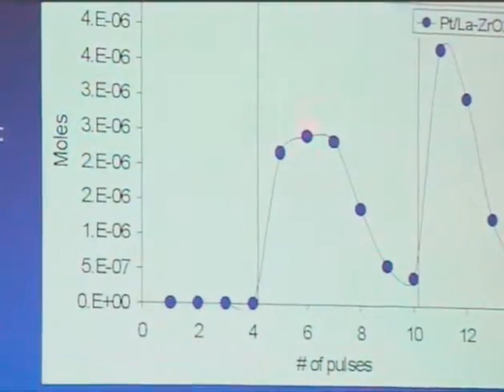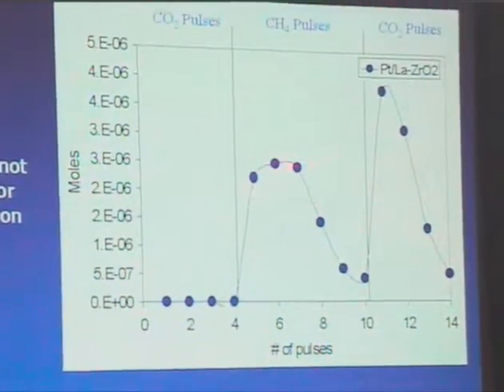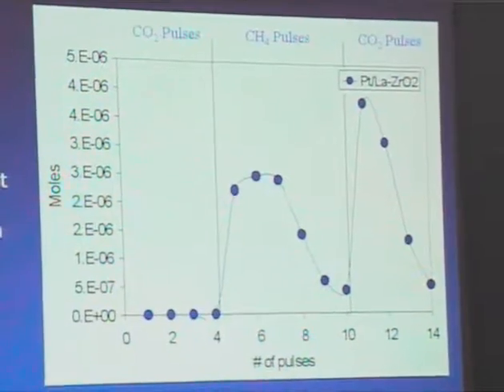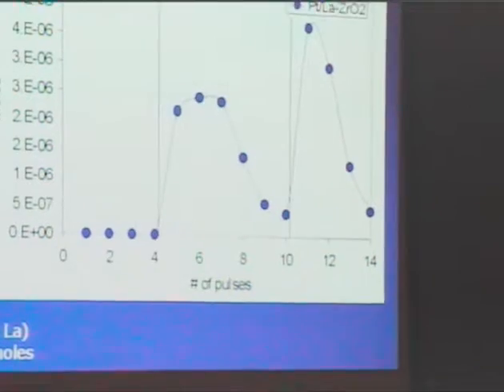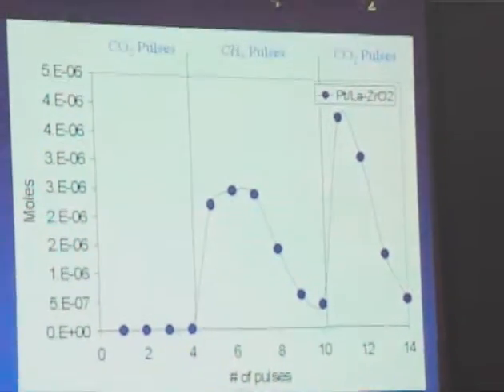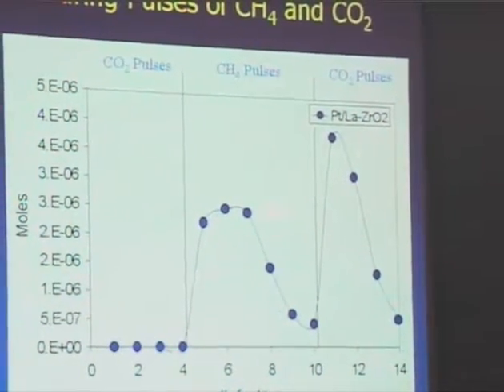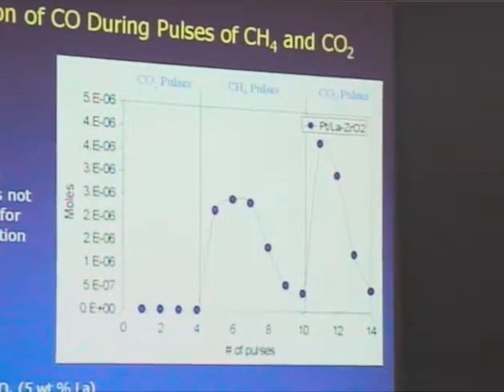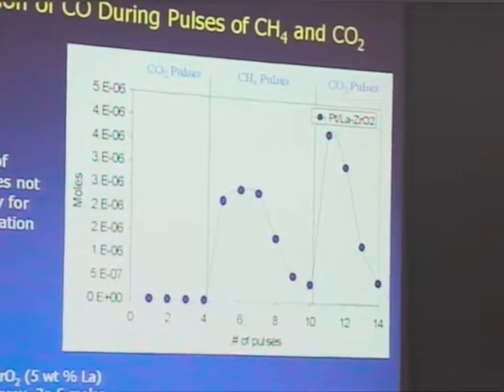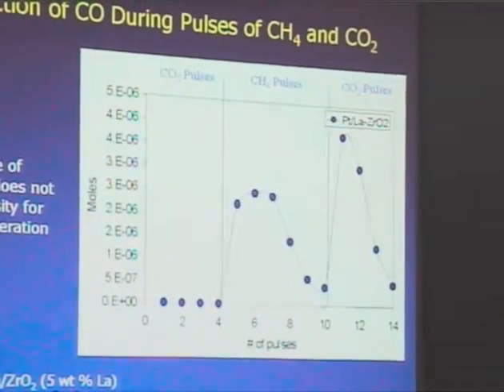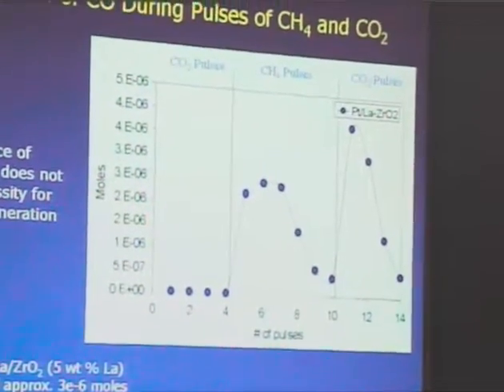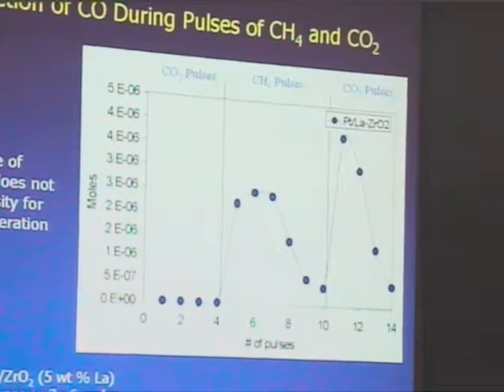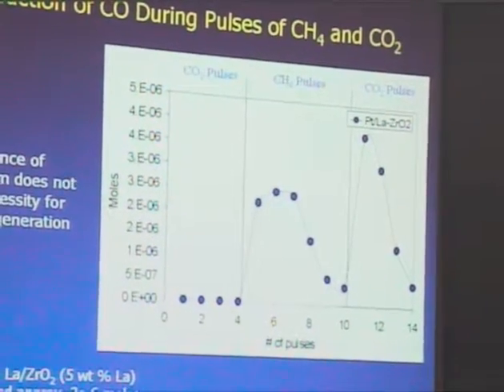One study that was interesting on this is that when we did pulses of methane after putting CO2 on the surface. So in this case, we have CO2 on the surface here. We've now done pulses of methane, as opposed to cases where we do pulses of methane first with no CO2 on the surface. We see more CO being formed when CO2 is present on the surface first, right? And so what we're thinking in that case is that when you put CO2 on the surface, lanthanum has the ability to form carbonates due to the basicity. When you put the methane in there, you now have a more reactive or an active carbonate species that can react with the carbon from the methane to form additional CO.